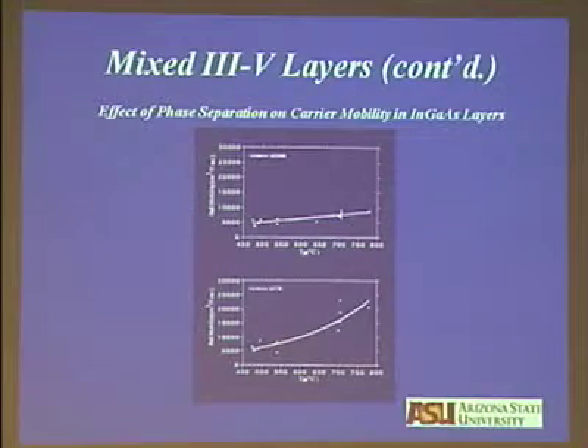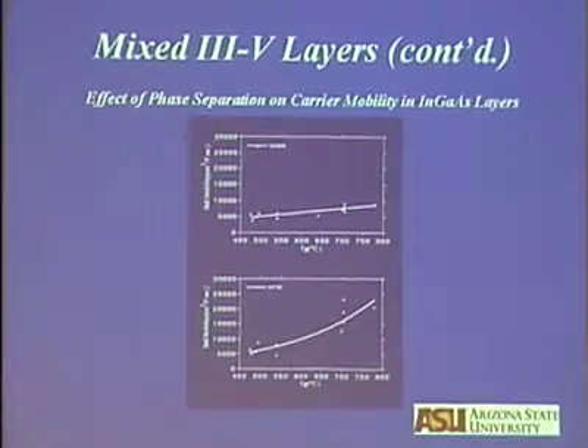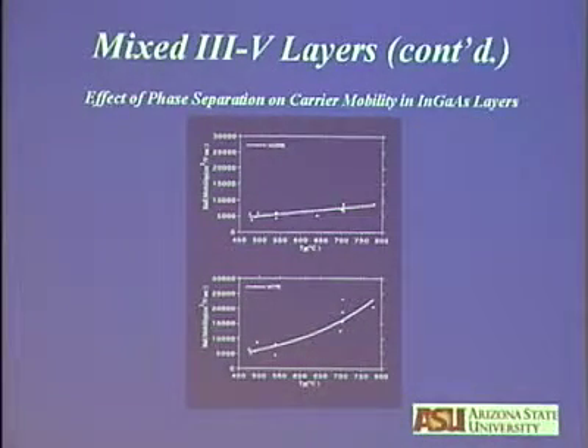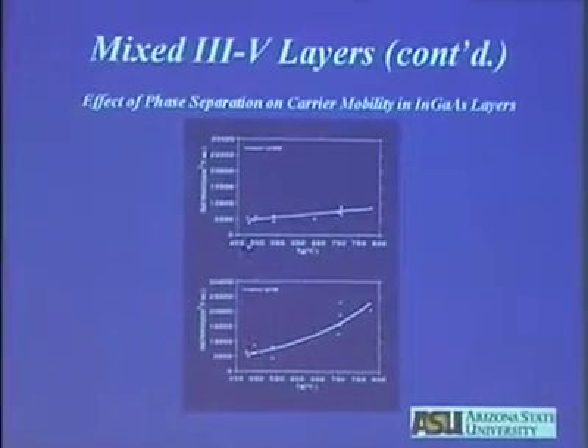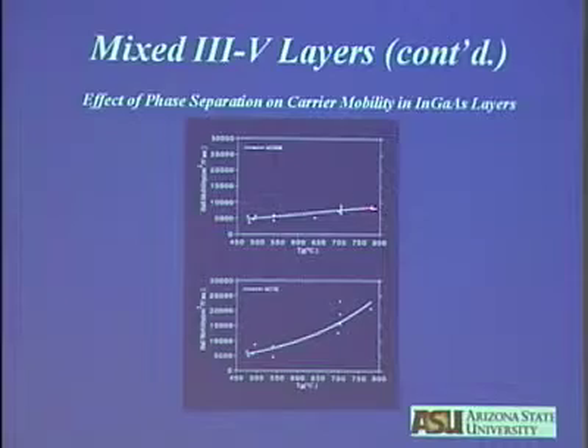Now, does phase separation have an effect on properties? That is an interesting question. You can keep studying physical metallurgy, you can study semiconductors, but does it have an effect on properties? We measured the carrier mobility in indium gallium arsenide. How did we do this experiment? We grew indium gallium arsenide of the same composition at different growth temperatures. And if you recall the phase separation concept I introduced, the higher the growth temperature, the smaller the composition difference between the end members. So if you measure the carrier mobility at room temperature, you see this dependence: the higher the growth temperature of your indium gallium arsenide layers, the smaller the effect on the mobility.